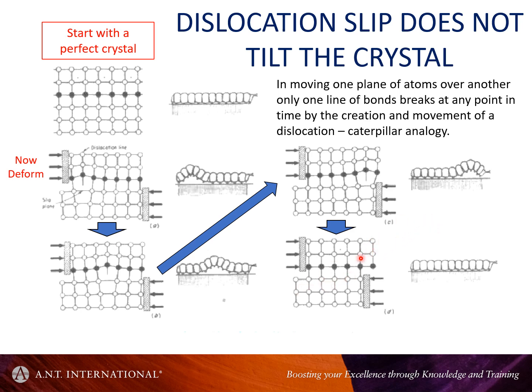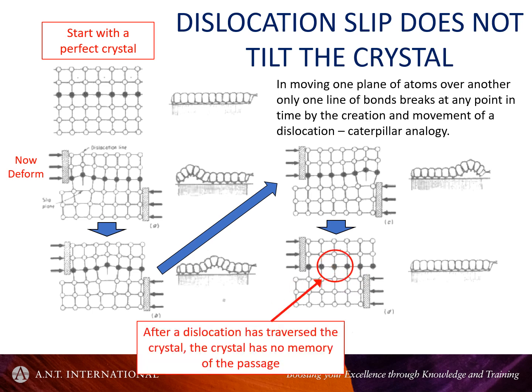This slip operation, this change in the shape of the material, may affect the constraints, may affect elastically the whole crystal. And you may get some rotation or bending, kind of hard to say, but it depends on the situation, depends what the constraints are. But there may be some effect just by simply deforming the crystal and changing the shape of the crystal in this way. There may be some effect on how this then fits into the remainder of the material. But for the atoms themselves, at the slip plane, there's no change in orientation. So there you go.